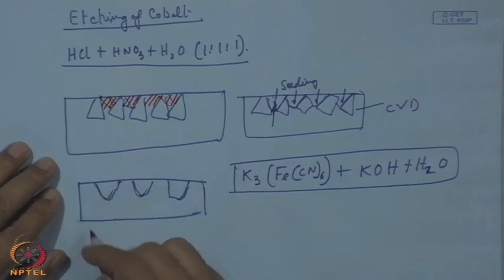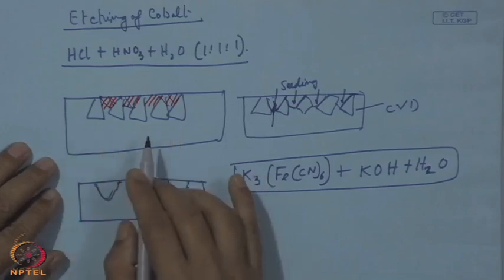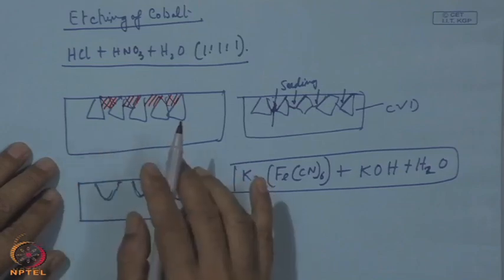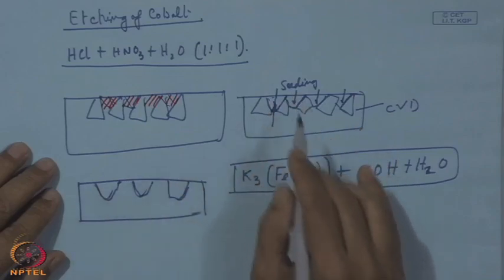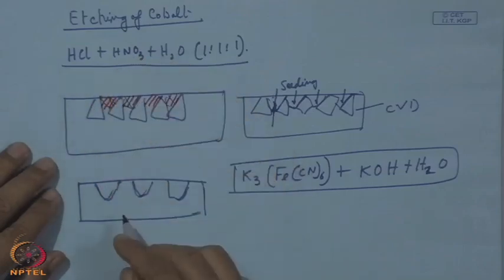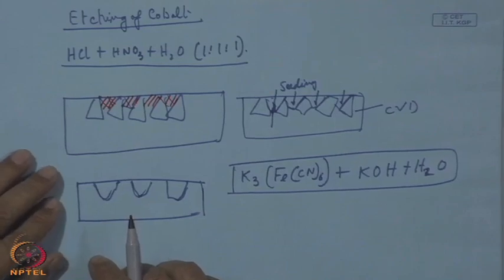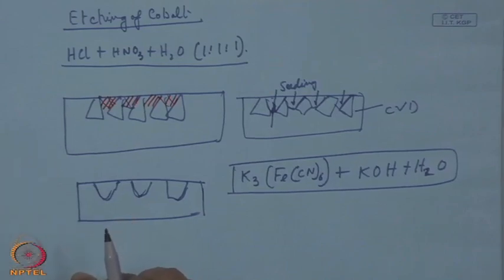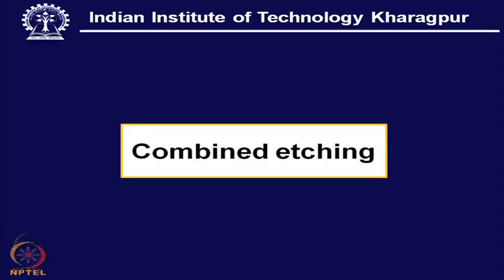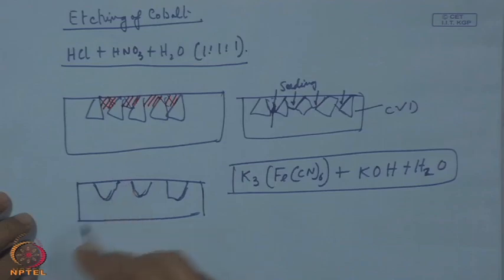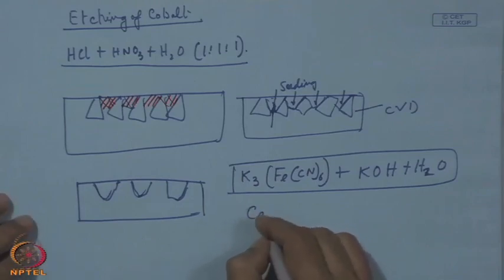So, here we have these cavities. That means the whole idea here is not only to get rid of this cobalt, but also to make some pocket for receiving this diamond dust, and it will be acting like seed. But here it is not just etching of tungsten carbide, it is actually combined etching. Combined etching means now we have pocket, but still cobalt is not yet deactivated. So, for deactivation of the cobalt, what is used? Caro's reagent.